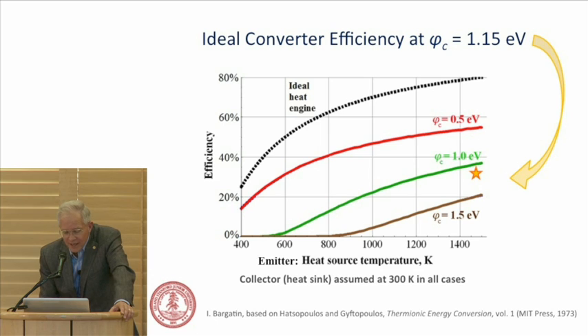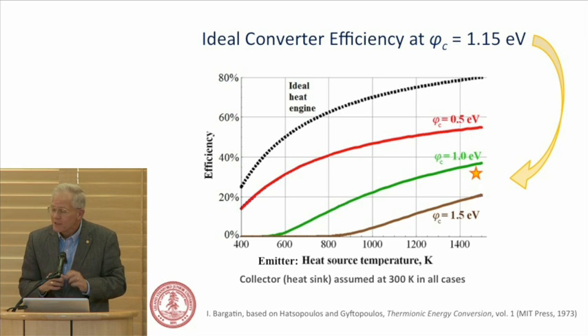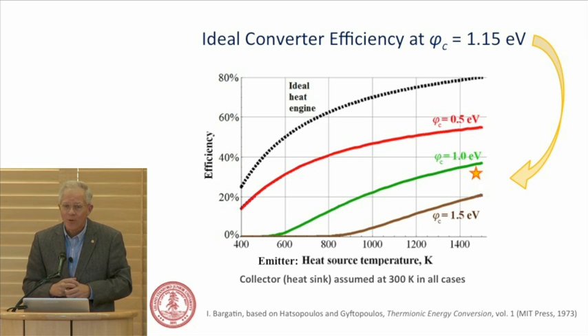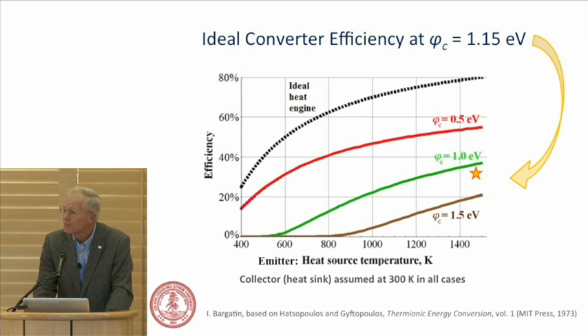If we indicate our lowest work function at 1.15, we are getting efficiencies that are in the range of 30% ideally. Again, we may not be rejecting the heat at 300 Kelvin. It may be a topping cycle, but compared to their initial work functions and without cesium, I think this is a very important breakthrough. We would be gearing up to do this experimentally.